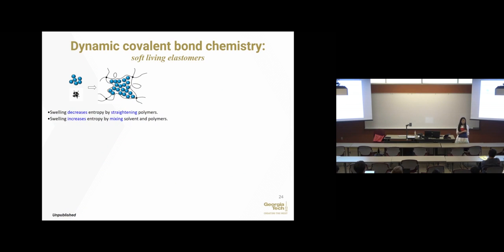So in that previous example I showed, it's a simple chemical reaction, photo dissociation. Now we want to move on to more complex chemical reactions. In the past, we worked with these pendant molecules that generate a chemical reaction. Now we think beyond, whether we can remodify the main network of the hydrogel. The idea comes from the following. From the theory, we know when you mix the solvent and the molecule, they want to mix because that will maximize your entropy of mixing. But meanwhile, the polymer chains are also straightened.